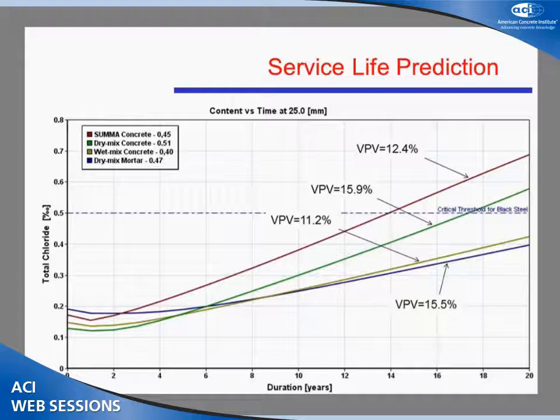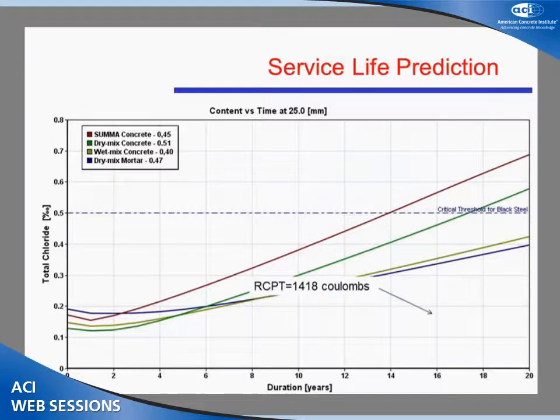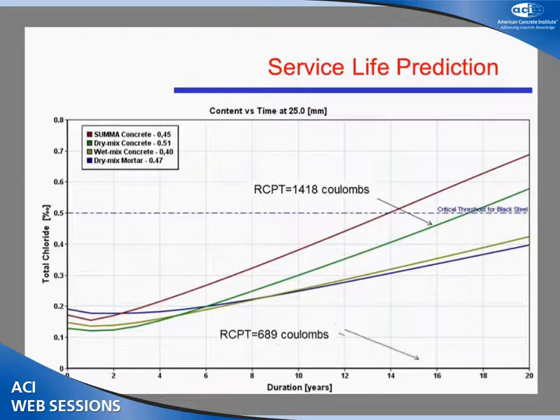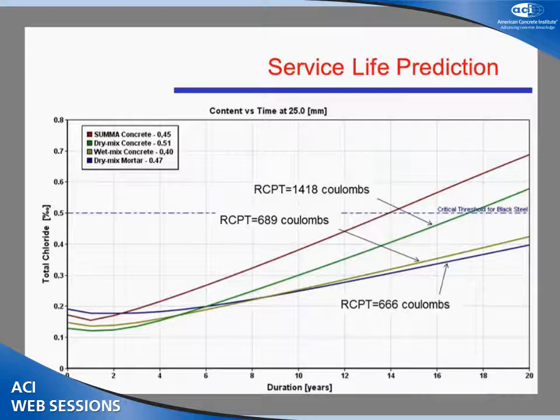The other thing I wanted to point out is coming up right now. What happens if we consider ASTM C1202, RCPT, that we presented just earlier? Well, this time it's not so bad. I'll talk a little about that later, but it doesn't seem so bad. You have, for example, the dry mix concrete that hits 1418 coulombs, just as a rough value. Remember, it's between 0 and 9,000. 9,000 is a critical value that you rarely get, and you want to be around 1,000 to 3,000 for something standard, where under 1,000 is excellent according to the ASTM norm. So this is not so bad. It actually somewhat correlates with this analysis.